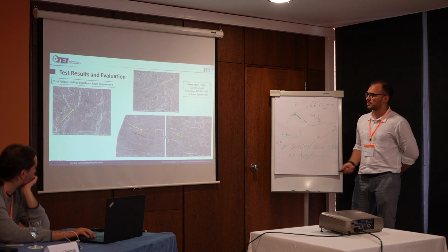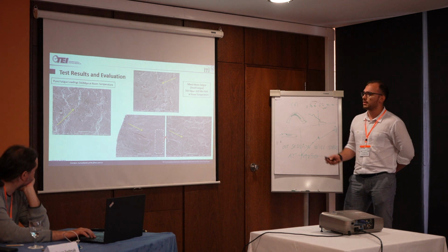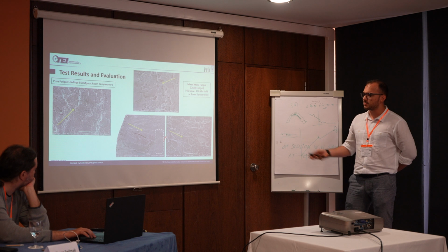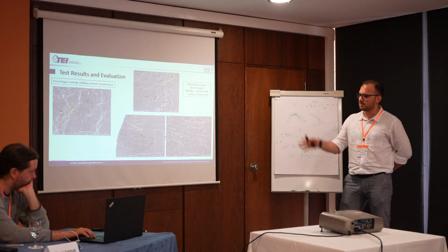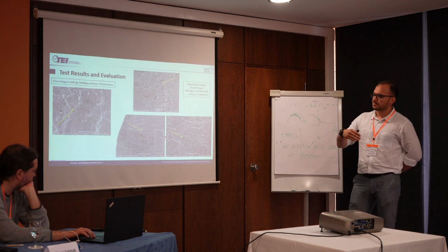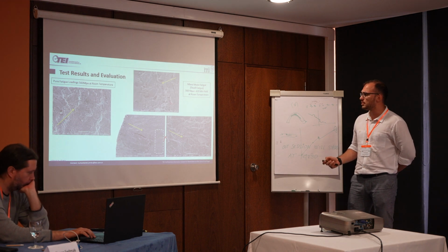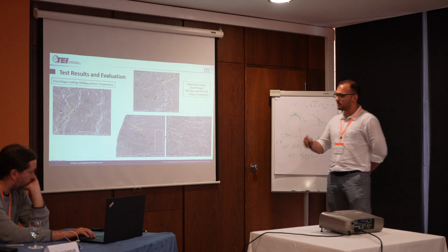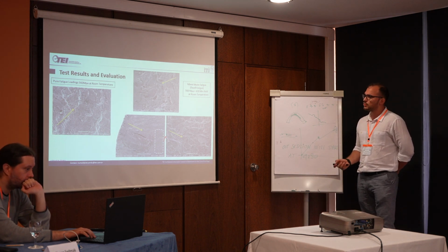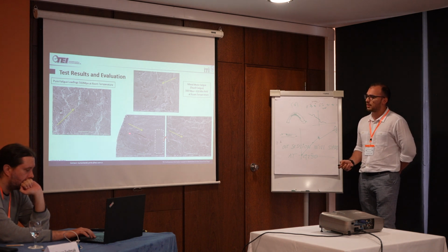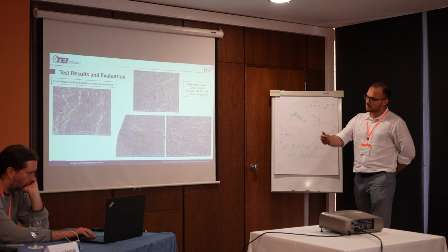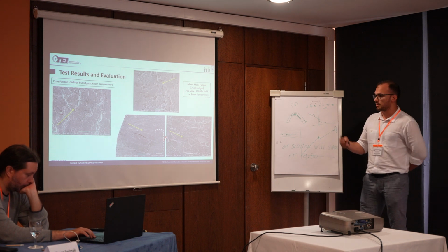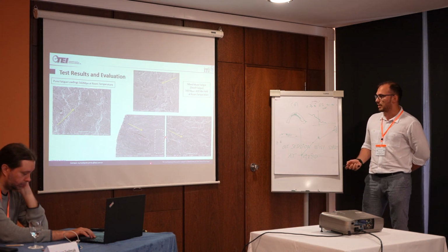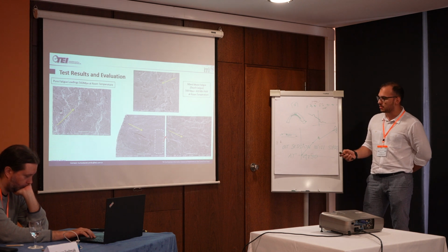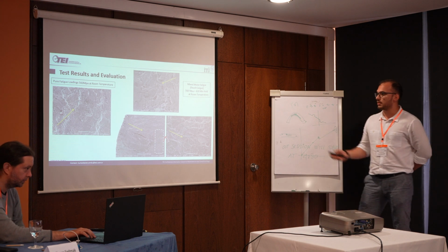And at room temperature, where the dwell fatigue decreases the life in rotating bending condition, we see some different features. For example, on the left side, again we have a non-dwell test, which seems pretty normal, has a couple of little secondary cracks, but we can see the striation network clearly. But here, once we applied the dwell, even at room temperature, we saw different features. For example, one of our specimens had a fracture in the subsurface region, which is a really unexpected situation. And once we checked the crack propagation side, we also saw some brittle behavior that we may consider.